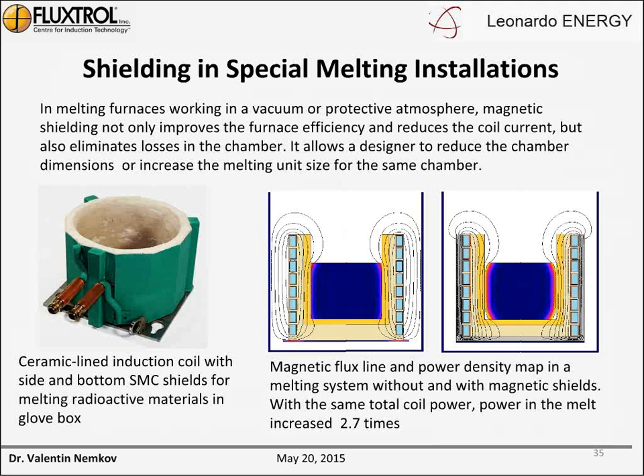Here we had, on the left side, a ceramic lined induction coil with a side and bottom soft magnetic composite shield for melting radioactive materials in a glove box. With applying of this shield we were able to increase the size of the coil for the same radioactive chamber and improve the parameters. With the total power of the coil the same, power in the melt increased 2.7 times.